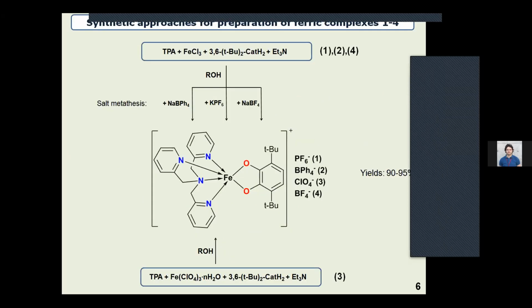On this slide, we can see the synthetic approach used for preparation of complexes 1-4. At the first stage, ferric chloride was reacted with TPA, and further reaction with deprotonated catechol is accompanied by the color change from yellow to dark blue-violet. Metathesis reactions with corresponding salts result in precipitation of desired compounds 1 to 4 as dark blue crystals.